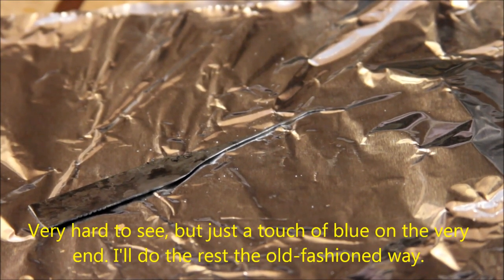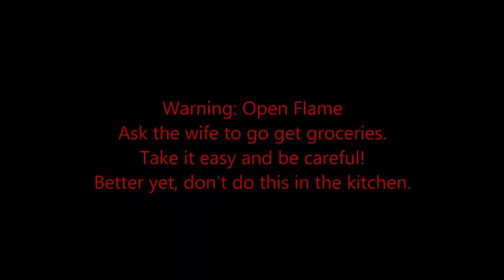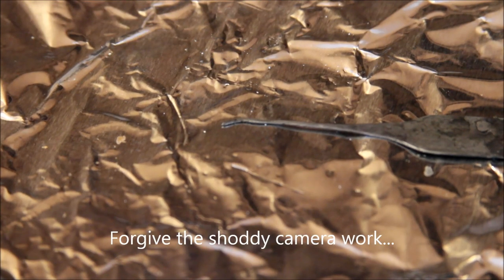I stopped when I started seeing a tiny bit of blue towards the end, which might be an indication that it was overheating. I'm now going to use a torch, which you probably should use outside to complete the tempering. This is very tricky, takes a little practice, and I think I actually screwed it up very slightly as we'll see later.